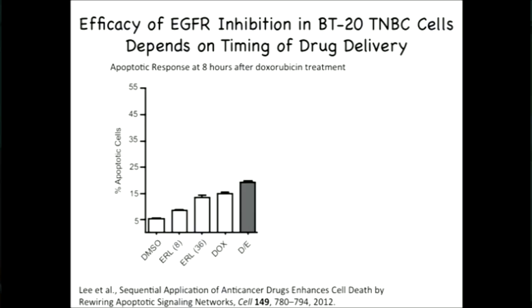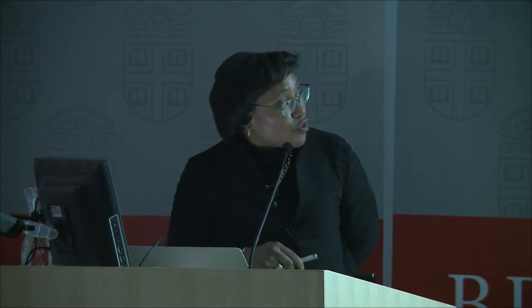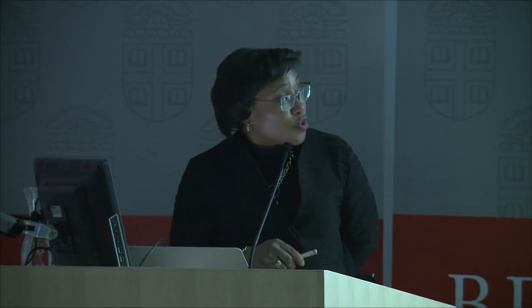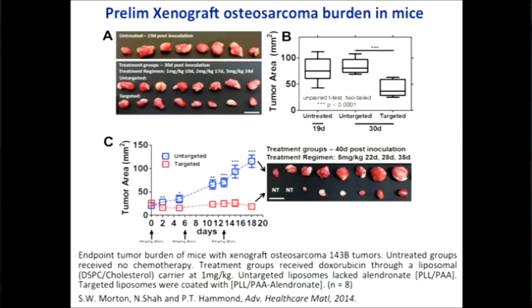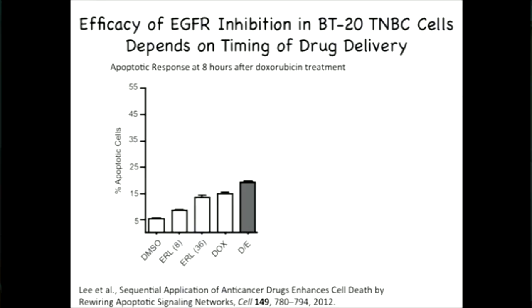You can see the untargeted doxorubicin. So we're treating them with a chemotherapy drug in a nanoparticle, but these are very rapidly growing tumors, and they essentially win. They're growing even though we are treating them with the drug. And we can compare this to the targeted system, and we see very little tumor growth, and in some cases, we can see some tumor regression.